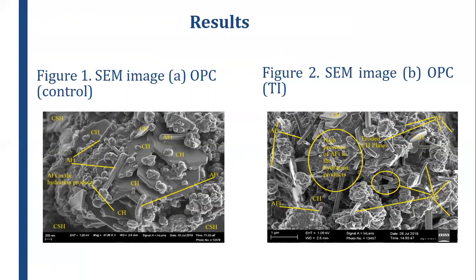uniform distribution of hydration products within the pore system of the control mortar, as shown in figure 1, that is SEM image A. OPC control showed uniform distribution of calcium hydroxide plates within the pore system, whereas there was ettringite formation within the control OPC. This was attributed to the initial gypsum added into the cement to improve workability and control the setting of the cement.